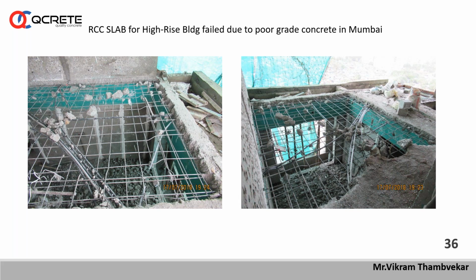Use of PPC is also very important, because all these PPC manufacturers add some amount of fly ash, up to 45-50%. I can't say it directly, but this is the regular practice. They add more than 30-35%. So the grade, the strength of your PPC material, one has to check properly, and of course all these trial materials should be tested before making any fresh concrete to use directly in RCC frame members.